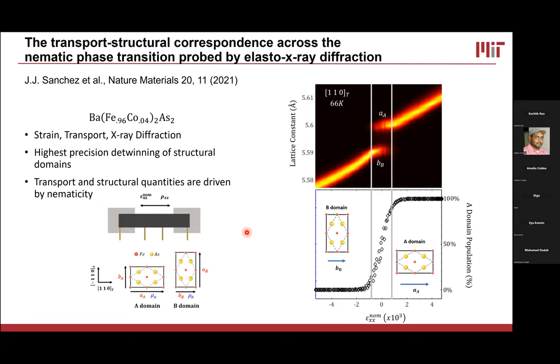So now I'd like to introduce the technique combination that I've made in my work at Argonne. I'm going to start by talking about a paper that came out 2 years ago. It's my first author paper, and it's my first paper using this setup of strain and X-ray diffraction. I think some folks here might be familiar with it, but I'm going to run through some of the biggest highlights of it. So in this work, I studied barium iron arsenide with cobalt doping. This is a doping where I still have a nematic transition and it's split by about 10 Kelvin from the spin density wave transition. And that gives me a temperature window where I can study the pure nematic phase.